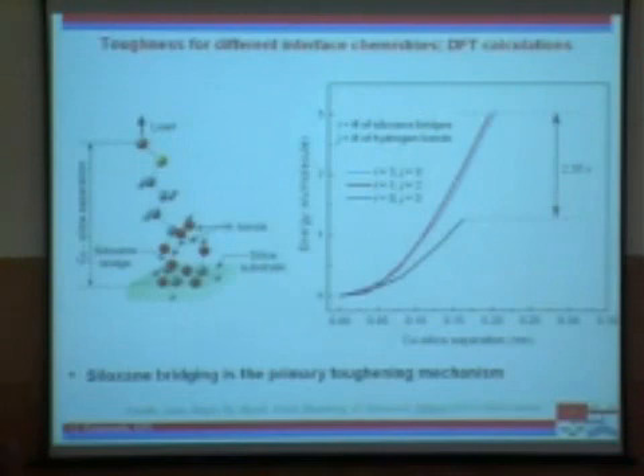So what does that do? Well, we did some theoretical calculations wherein you take a single molecule and stretch it, and what you find is the energy required to stretch and break the molecule, in the case of where you have just a hydrogen bond, is shown over here. And once I add a SiO-Si bond, then you're nearly doubling, increasing by a factor of 2.5. And that corresponds very well to the experimental measurement that I showed you.